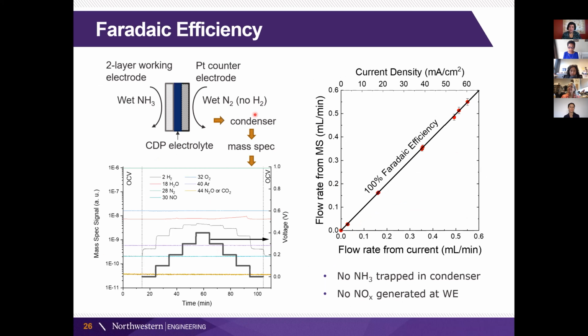We put a mass spec on this side. We have to have a condenser here, and then we detect what's coming out on this side. So what we see is when we detect the hydrogen that's produced and compare that to what we expected from the flow rate, that's exactly at 100% efficiency. We wouldn't be able to tell if ammonia is coming across because we have this condenser, but we look at the water and see that the pH hasn't changed. So we know we're not leaking ammonia across it.